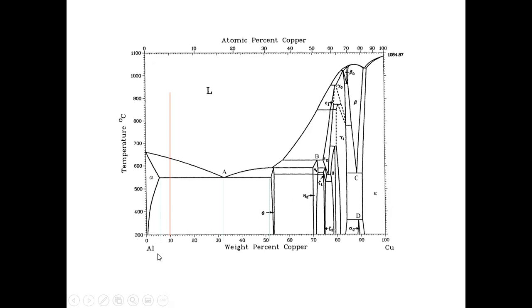At least for aluminum alloy, for aluminum copper, typically what we do is add a little bit of copper into the aluminum. So the copper serves as a solid solution strengthening mechanism. We make this alloy stronger, yet we do not lose a lot of the advantage of the lightweight of this metal, right? Aluminum is very light, but it's very soft. So we strengthen aluminum with a little bit of copper added.